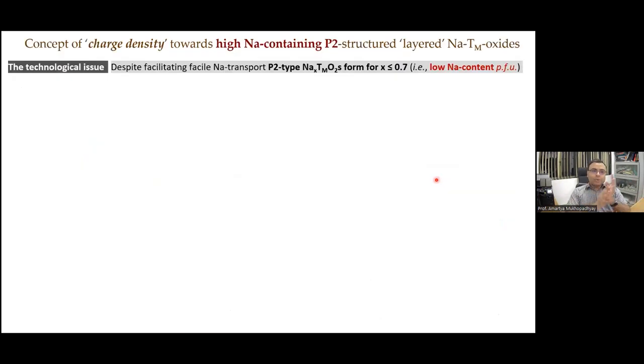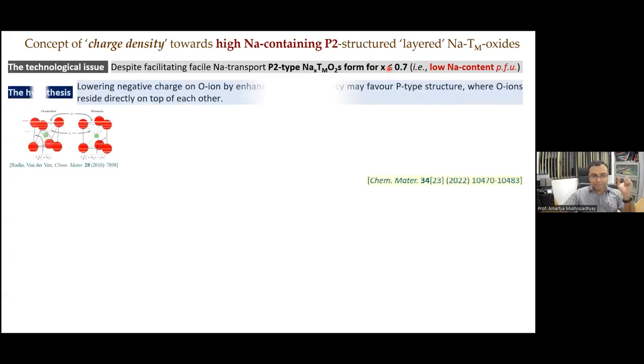moving to the last topic of today, that is how to design and develop a high sodium containing P2 structured layered sodium transition metal oxide. Now, as a recap, the P2 type structure is important because it renders sodium transport facile, and can lead to very high rate capability compared to the O-type structure. However, the main bottleneck of the P-type structure is the low starting sodium content per formula unit, which is typically 0.67 to 0.7 per formula unit, which is bad because the cathode material is supposed to be the reservoir for sodium ions in a sodium ion cell.